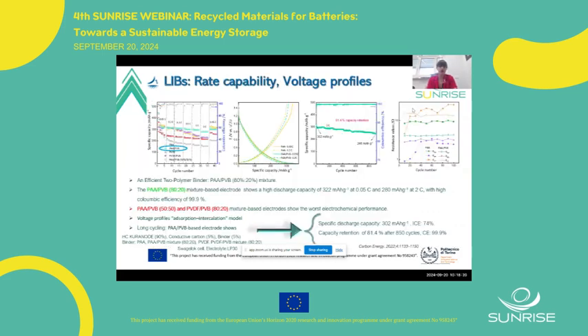All the measurements were also performed for hard carbon laminates for lithium-ion batteries, and as we can see, the PAA-PVB based electrode, 80-20%, the green one, shows the best performance from low C rate to high C rate, and also a very high initial Coulombic efficiency of around 74%, but upon cycling it reached near 100%, 99.9%.